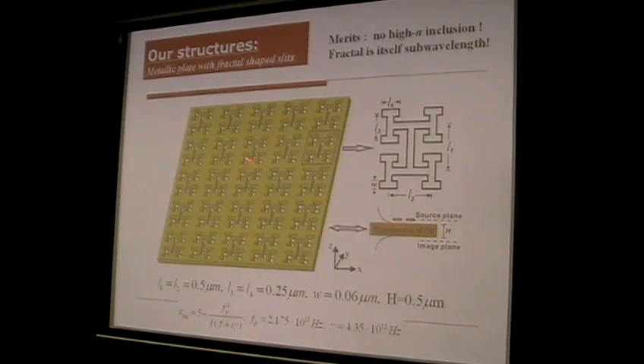Because our structure is sub-wavelength along all directions, this structure can actually be viewed as local resonators. When it is on resonance, the coupling between these two will give us a so-called TM polarized surface plasmon. The coupling from this resonator to this resonator will produce a running wave along this direction. And this mode will give us a TM polarized surface plasmon.